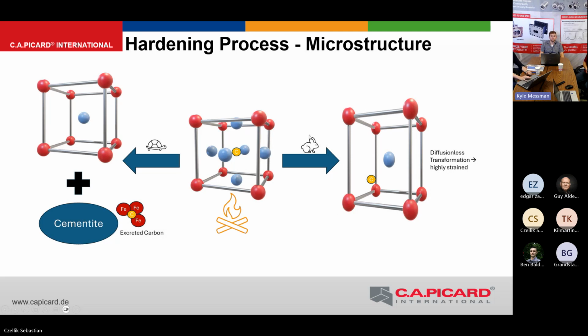We want to quench it, so cool it down very rapidly. And then we have a diffusionless transformation, and the carbon cannot go out of the lattice because it's not fast enough. And so we have a highly strained lattice. What we are doing while tempering, on the one hand, we try to build some carbides when we do secondary hardening, but we also want that the carbon gets a little bit of energy so that it can move out of the lattice and it's not that highly strained and the stress is reduced.